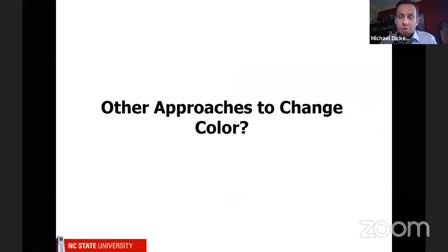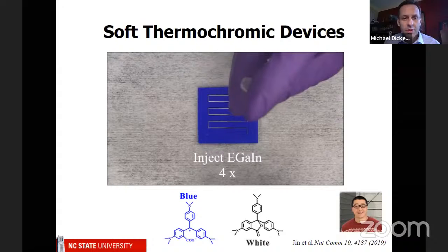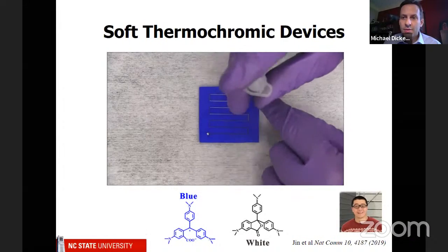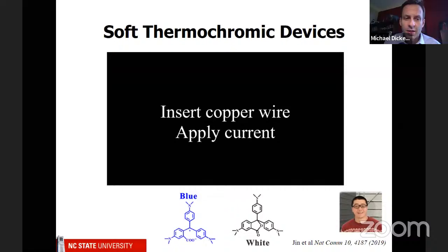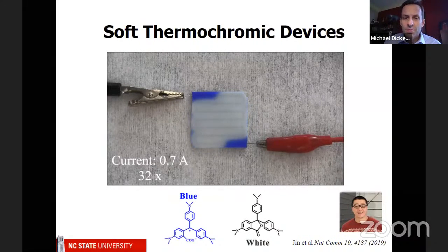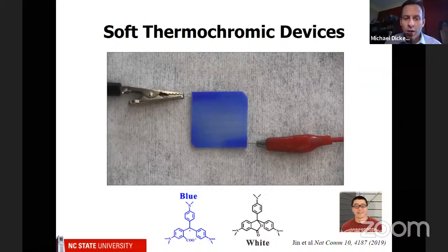But there are other approaches to changing color? And the answer is yes. Otherwise, I wouldn't have said this. So what we did was we took liquid metal and we injected it into silicone, and that silicone had a special pigment in it that looks blue. When you heat up this pigment, the color changes to white because there's a change in the pigment due to temperature. These are called thermochromic. Thermo meaning heat, temperature, and chromic meaning color. So it's soft because it's made out of liquid metal. It changes temperature because of electricity, and it's chromic, meaning it changes color.